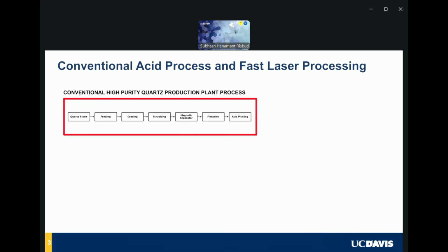And so the next thing I want to talk to you about is probably more related to laser processing, which is one of my grad students doing this, because the quartz sand we get from Brazil is impure, and people have used all kinds of chemical techniques of flotation, acid pickling, scrubbing, all that, to purify the sand to higher levels of content of silica, and that's high purity is what we desire for a lot of applications. So one of my students has been doing this work on basically using the quartz stone and moving it into the next stage of pickling and acid production. But instead, we took the approach that instead of doing it this way, let's try doing something else.